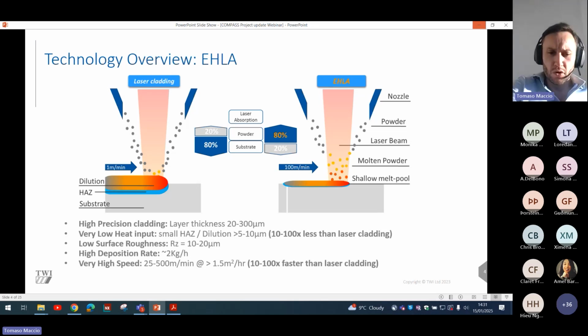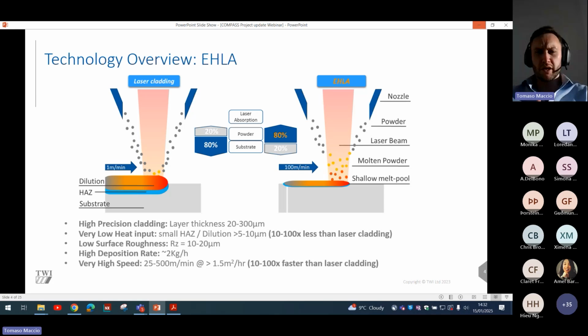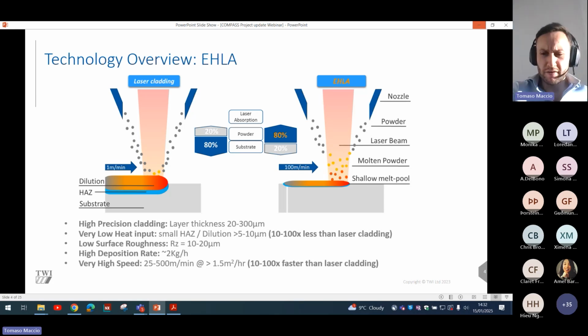coming through the substrate. Whereas with EHLA, the melting is happening above the substrate. The melting of the powder is happening just above the substrate and then it is sprayed onto the substrate, almost similar to thermal spray. So it's a buffer between thermal spray and laser cladding. It's got a metallurgical bond like laser cladding, but it's also been sprayed like thermal spray. So we end up with a much smaller heat affected zone and dilution layer. With this, we can create high precision layers from anything from 20 micron up to even 300 to 500 micron layers.